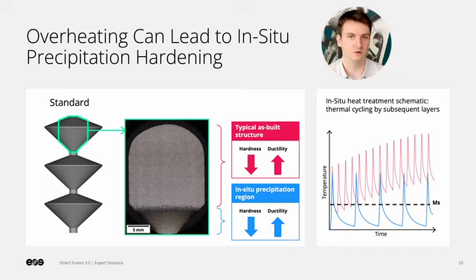What plays an important role here is that this job was built with a minimum layer time. In other words, the machine waits every layer until a fixed time has expired. As a result, there is plenty of time to cool down between layers and form martensite in the bottom of the cone, since the exposure area there is very small. The blue curve shows this schematically.